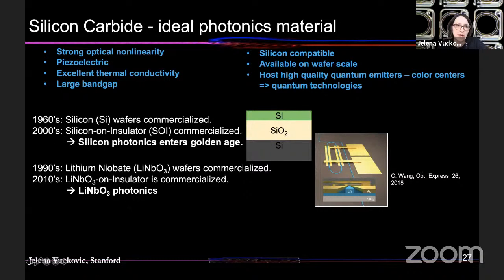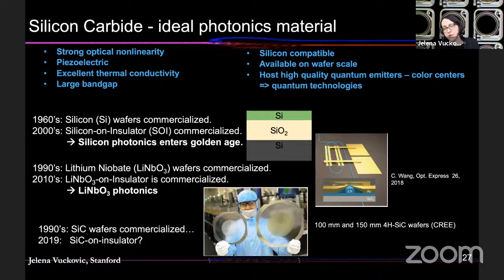And then the last 10 years, people have been working actively on thin film lithium niobate. That was, again, when it was commercialized, and that was, again, 20 years after bulk lithium niobate was commercialized. And as of last year, when we started actively working on silicon carbide photonics, there was no commercial silicon carbide on insulator, although it's been a long time, 30 years since bulk silicon carbide was commercialized, and you can get it even on 6-inch wafers, and it's much cheaper than diamond.